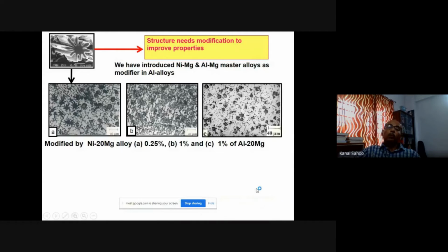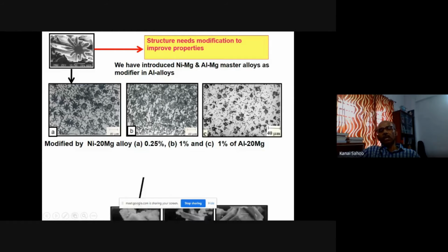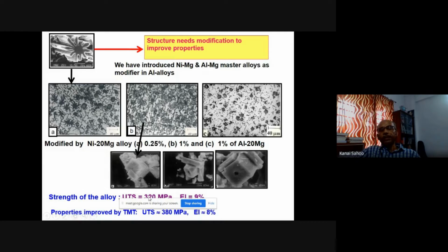The moment we modify, imagine I have introduced this nickel magnesium in aluminum alloy, this is the first time, and I have taken a patent on it. So that structure totally modifies, the spheroidal shape changes from this dendritic, star-shaped structure to this. So strength 320 with elongation almost 9%. By further post TMT, thermomechanical processing, the structure is further improved to 380 MPa. And some of the precipitates I have extracted from the matrix.